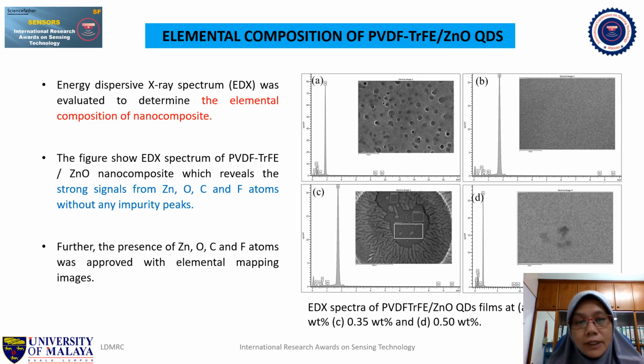The purity of the nanocomposite was investigated by using EDAX. We have obtained EDAX spectrums, and the spectrum reveals that there are strong signals coming from zinc, oxygen, carbon, and fluorine atoms. There are no impurity peaks indicated by the EDAX spectrum. The presence of zinc, oxygen, carbon, and fluorine atoms was also confirmed with elemental mapping images.